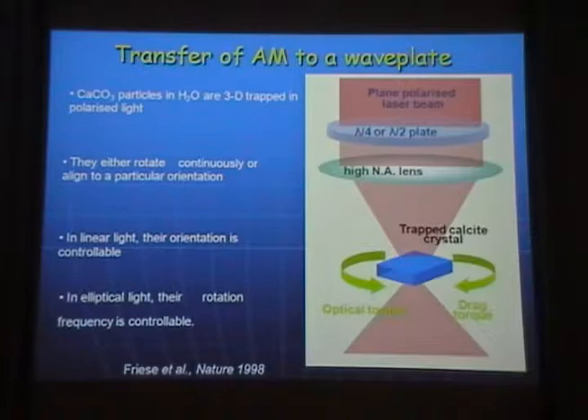Okay, so now in this case, calcite crystal is known to be very highly birefringent, so I take a shard of calcite crystal and I put it under my optical tweezers. Okay, so what happens with this calcite crystal which is dispersed in water? It will be three-dimensionally trapped, so that's one thing we wanted to do. And they either rotate continuously or align to a particular orientation.